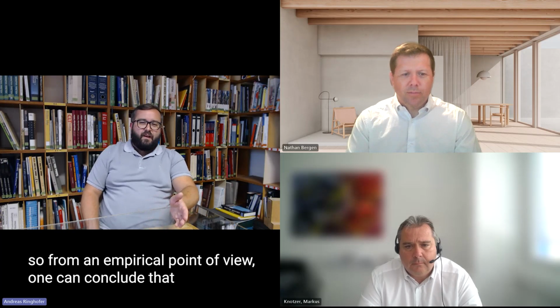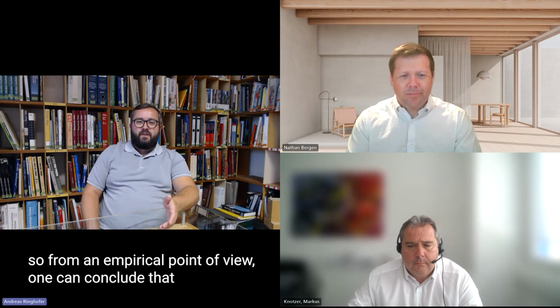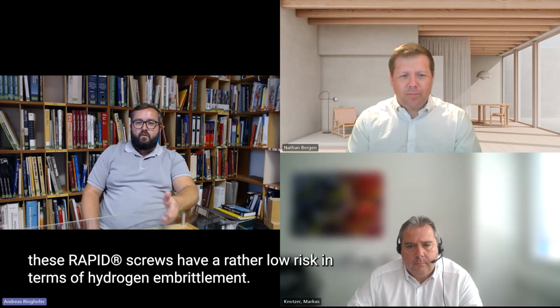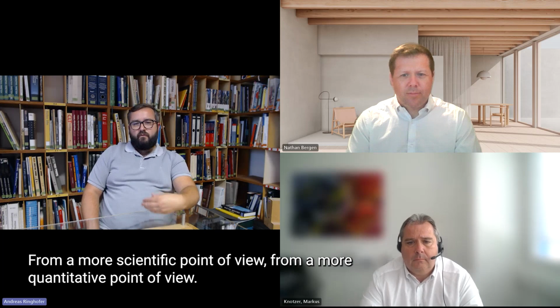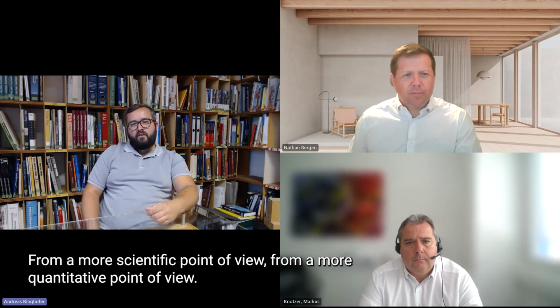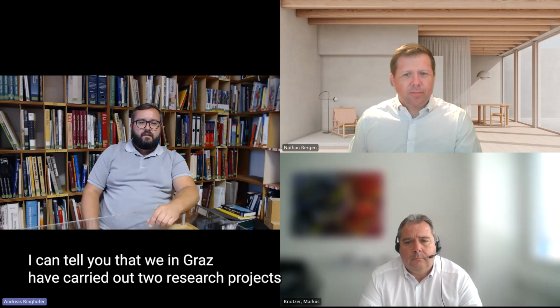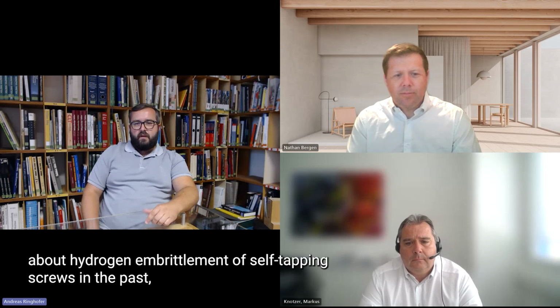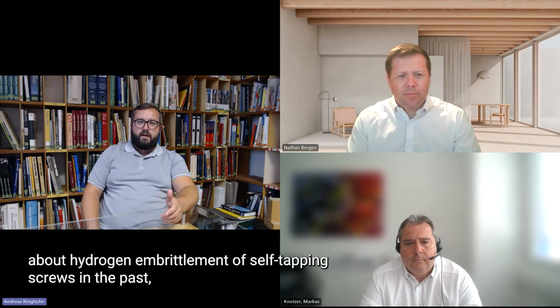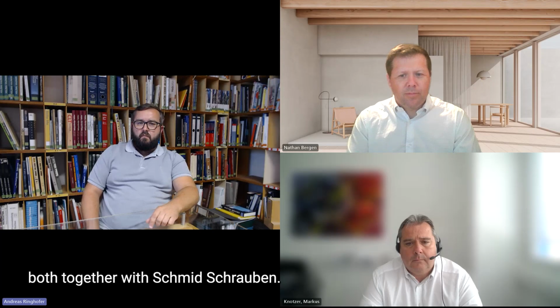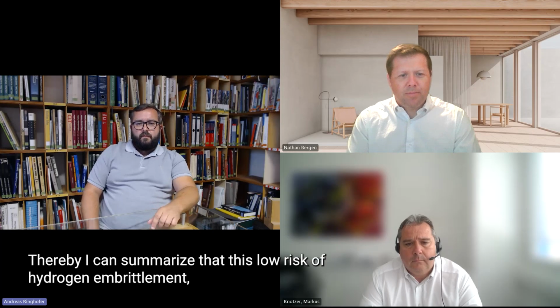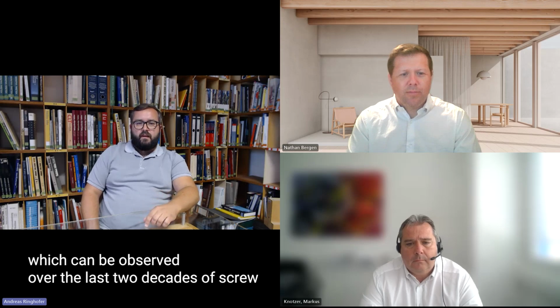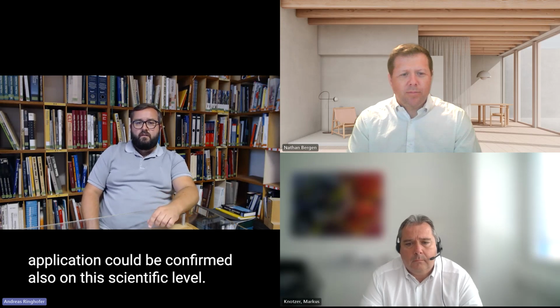So from an empirical point of view, one can conclude that these rapid screws have a rather low risk in terms of hydrogen embrittlement. From a more scientific point of view, from a more quantitative point of view, I can tell you that we in Graz have carried out 2 research projects about hydrogen embrittlement of self-tapping screws in the past, both together with Schmid Schrauben. Thereby I can summarize that this low risk of hydrogen embrittlement, which can be observed over the last 2 decades of screw application, could be confirmed also on this scientific level.